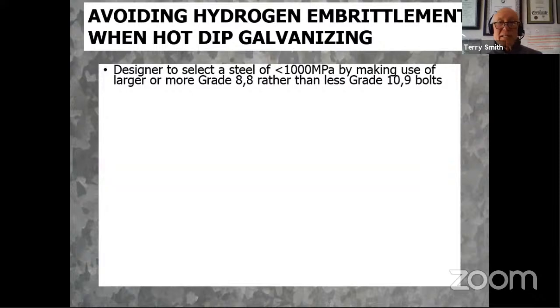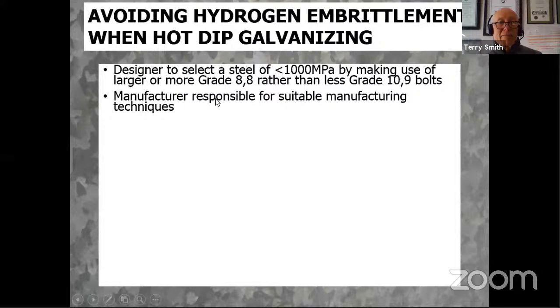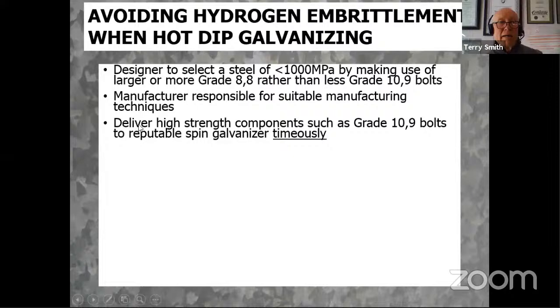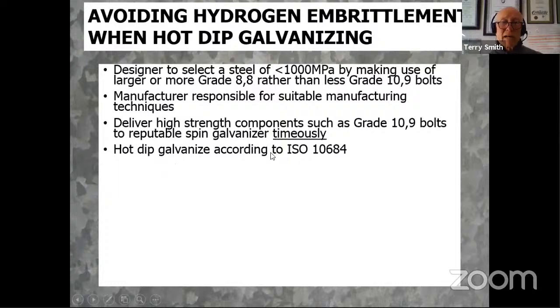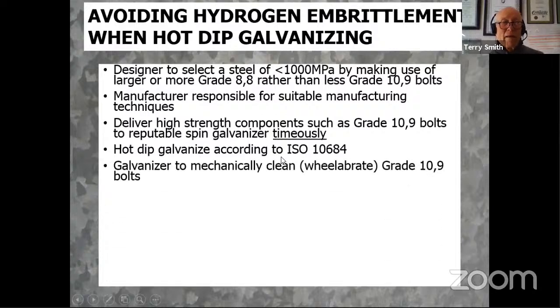Designer to select a steel of less than 1,000 MPa by making use of larger or more grade 8.8 rather than less grade 10.9 bolts. Manufacturer responsible for suitable manufacturing techniques. Deliver high strength components such as 10.9 bolts to a reputable spin galvanizer. Very important: hot dip galvanize according to that standard.